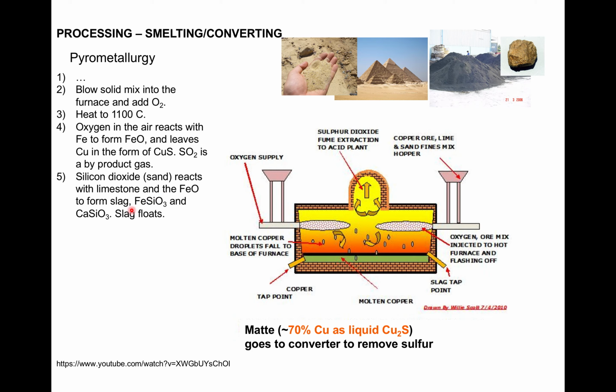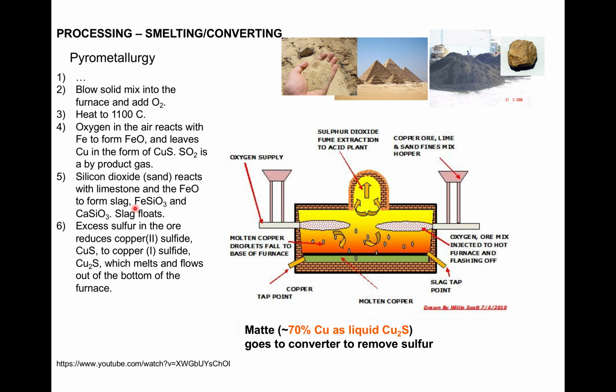The density of slag is lower than the density of the copper sulfide liquid matte, so the slag floats, the matte sinks. We can put an outlet for the matte, and we can put an outlet on the right side for the slag, and we're literally tapping those, and we allow the two liquids to flow out of the base of the smelter.